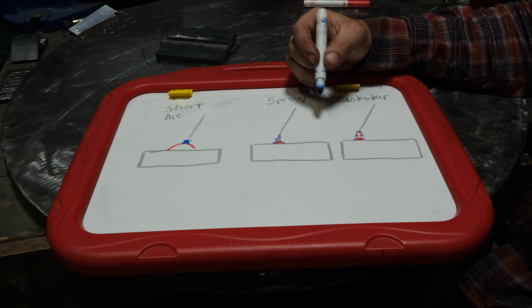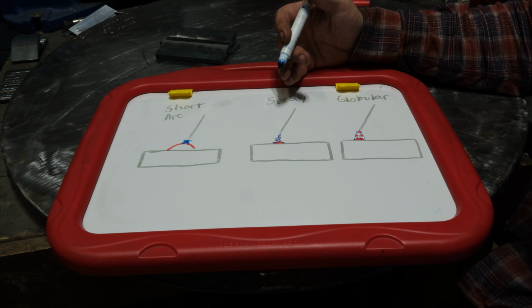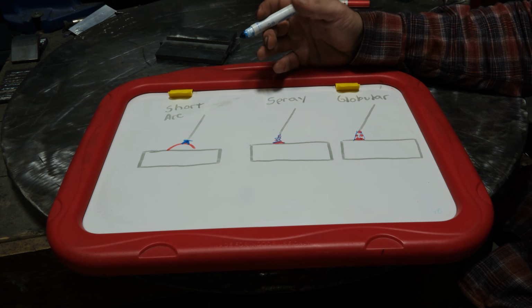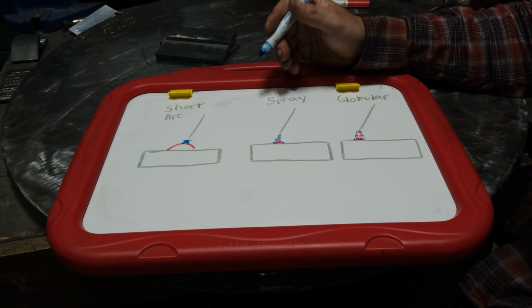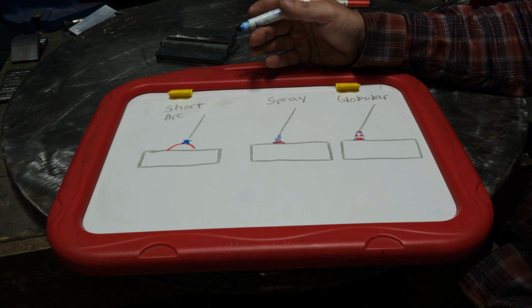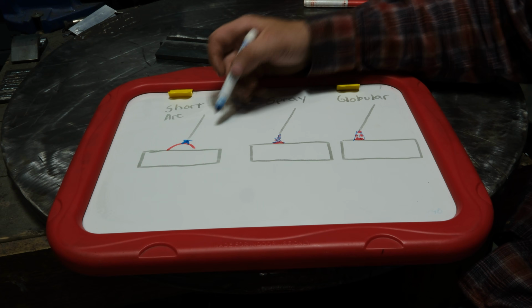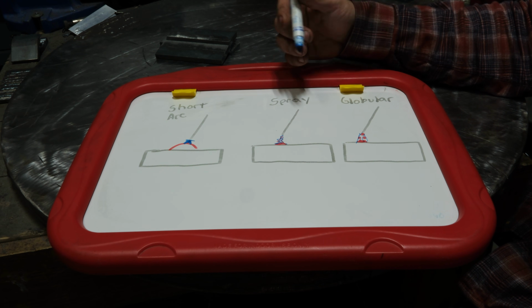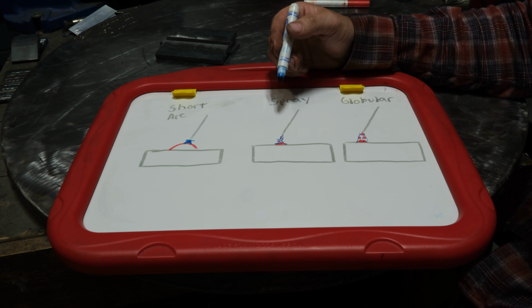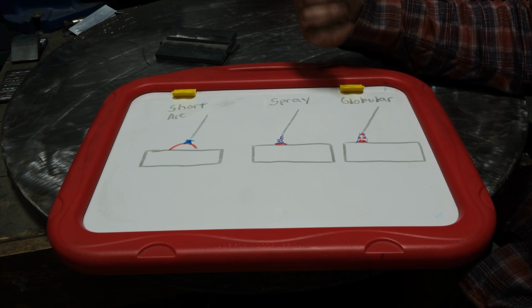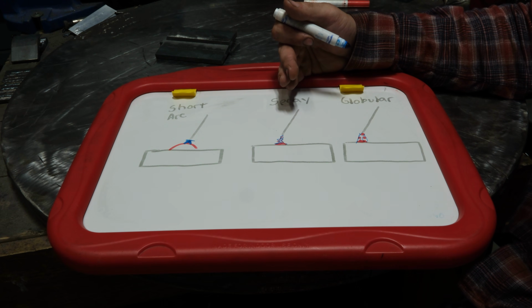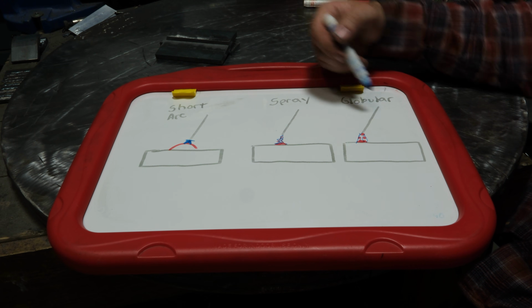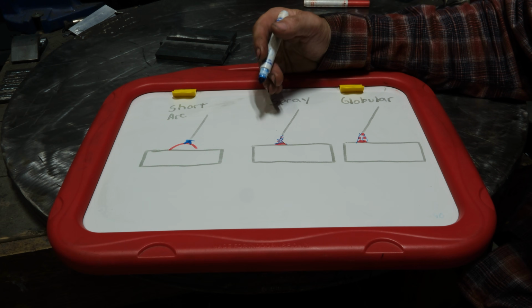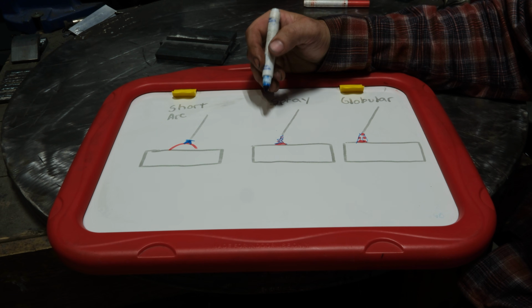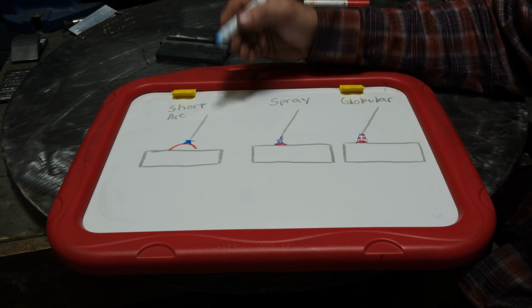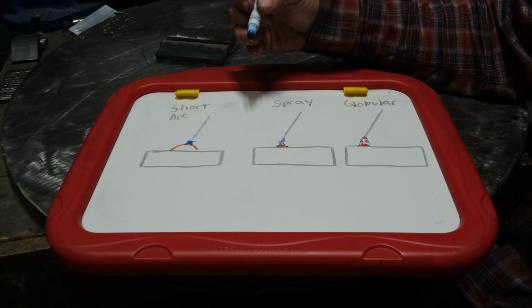Now, the reason I brought these up is so that you understand that if you're in the short arc process, which means that you're typically below 200, 215 amps, maybe a little bit more depending, under about 23 volts, and you're using C25 or 100% CO2 gas, you are running in the short arc process. If you're running 25 to maybe 30 volts and you're running spray mixture, then you can spray, or globular with 100% CO2, you get that. But what you need to understand is that these processes here produce more root fusion, more sidewall fusion typically, and just overall better performance on thick steel that you simply can't get from the short arc process because of how the heat input works.